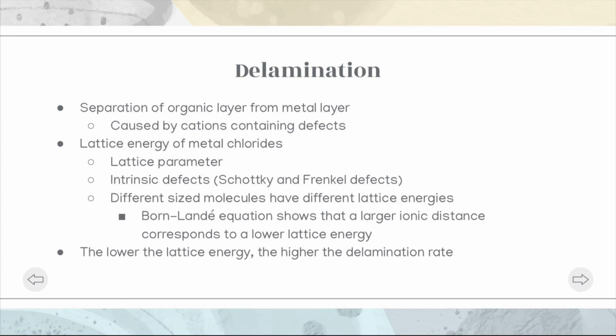The lattice parameter can be defined as the distance between 2 points on the corners of a unit cell. Research conducted by Sharma et al. indicates that potassium chloride nanoparticles have significantly larger lattice parameters than their bulk counterparts. It was deemed that intrinsic defects are responsible for the expansion of the lattice parameter of potassium chloride nanoparticles. These defects were introduced through ball milling, a method that grinds materials into an extremely fine powder, with the defects consequently generating surface stress on the nanoparticles.